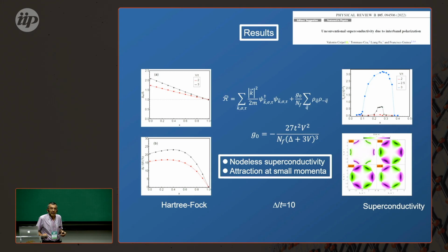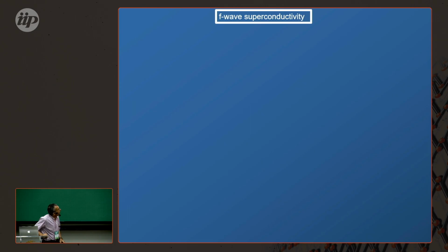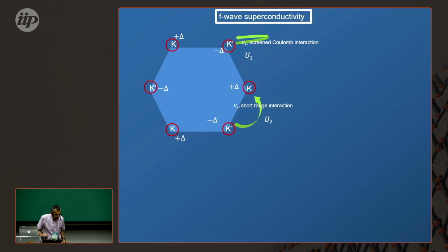So you have a gap function which changes sign. That means that a short-range scatterer, which takes you from one valley to the other, is pair breaking. And actually, it's pair breaking exactly in the same way as a spin-1/2 impurity is pair breaking in an S-wave superconductor. So you can take all the Abrikosov-Gor'kov equations and apply them to an F-wave superconductor. You can think of it in terms of intra-valley and inter-valley interactions, what Andrey Chubukov was calling U1, U2, and U3. What I call here U2 is what he called U3.